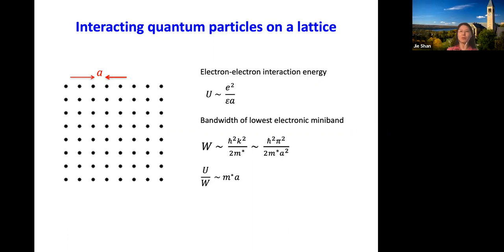So here's the recipe for strong correlation. If you want this ratio to be big, you look for a system with large mass and with large distance A, and that's the low density limit. In a solid state system, the mass is typically something like 10% of the electron mass, and the dielectric constant for semiconductors is something like 4 or 5. So the ratio can be larger than 1 if the separation is on the order of 10 nanometers. So this is the new length scale that Moire superlattices introduced.